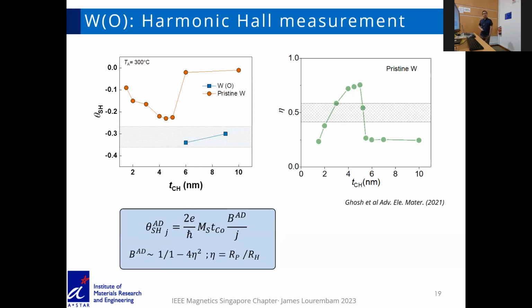However, there is a caveat there, because in the calculations we assume that there is no planar Hall effect, but in fact this value of eta, which is the ratio of anomalous to planar Hall effect, is pretty high. This is important because if eta is, let's say, about 0.5, then if you use the real value of eta, the value becomes unreasonable. So the assumption here is eta equals 0. We have to consider that there is a caveat in this value of spin Hall angle.